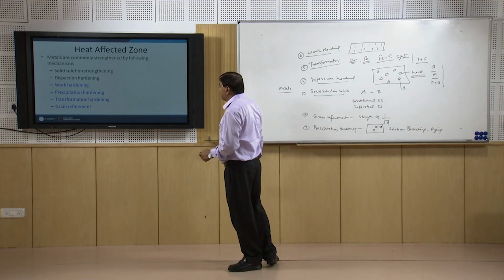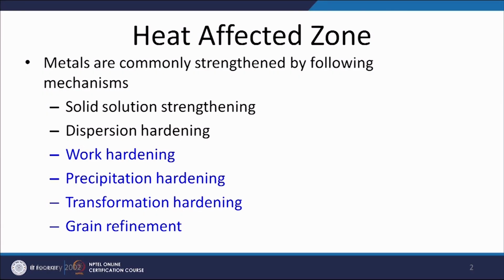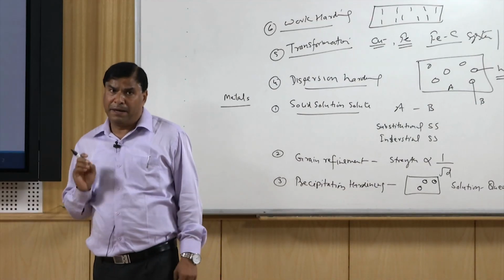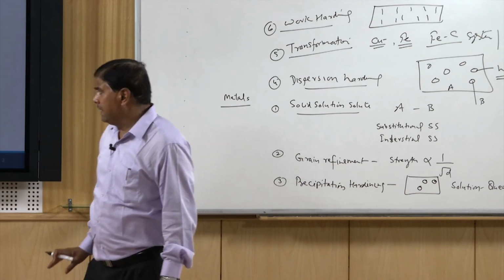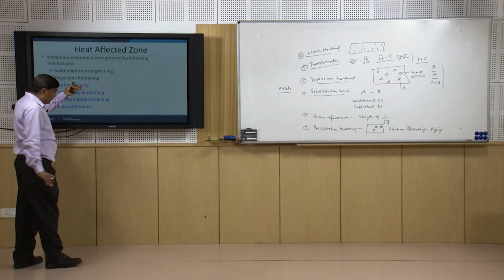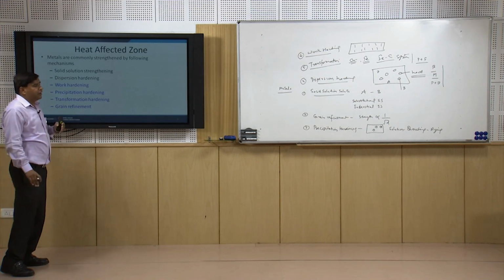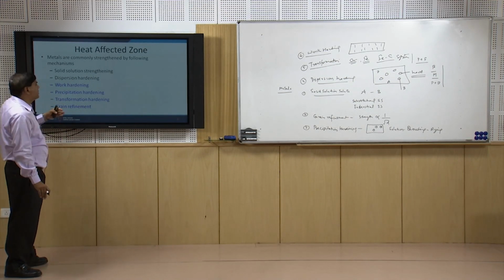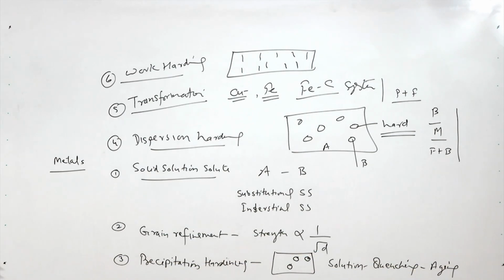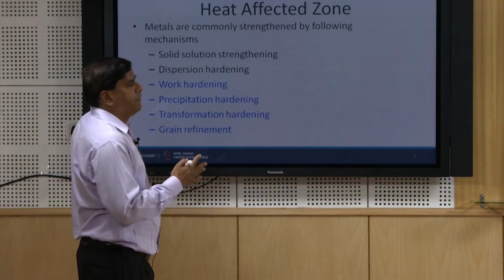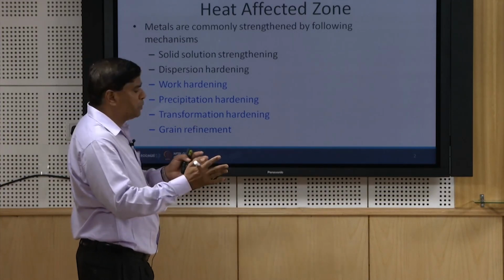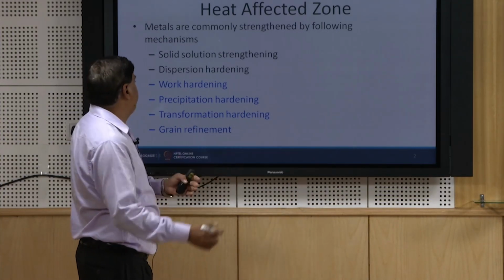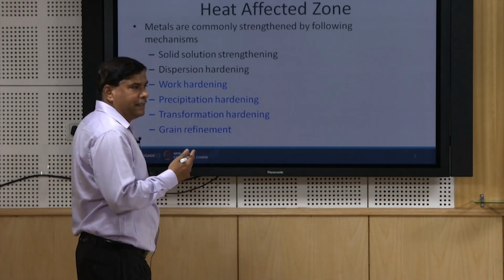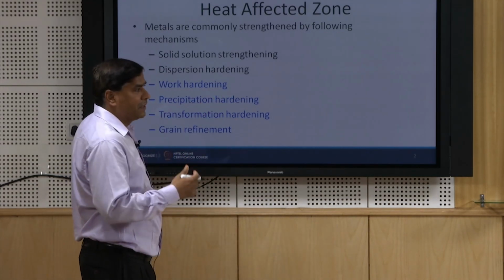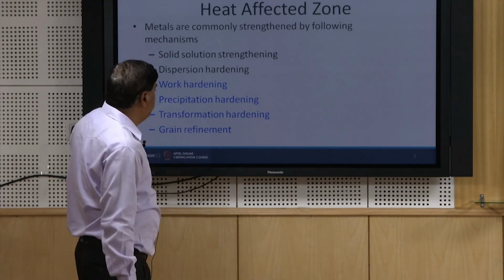The solid solution strengthened and the dispersion strengthened or hardened materials are somewhat less affected by the heat applied during welding, while in case of work hardening, the effect is lost due to annihilation or recovery of the dislocations. In precipitation hardening, due to the application of heat in the heat affected zone near the fusion boundary, these precipitates either get coarsened, or get lost, or get dissolved. So, the metal gets softened.